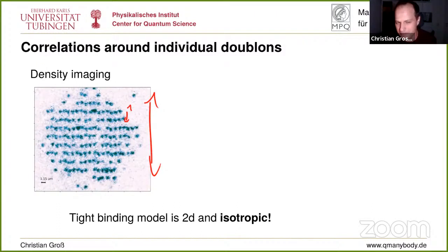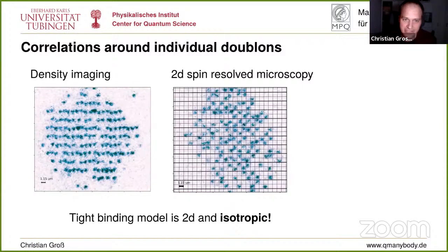For this, we have to pay a price. It makes, first of all, our system only half the size in the vertical. And second of all, the atoms, when we prepare this system, come from a 3D isotropic cloud. So they have to heavily reorder to have half of the atoms only vertically than horizontally. And that costs us temperature that we can reach. And this is already an introduction to version 3.0 later. So it costs a price if you do it like this. But nevertheless, we can use our imaging technique and do 2D spin resolved microscopy.